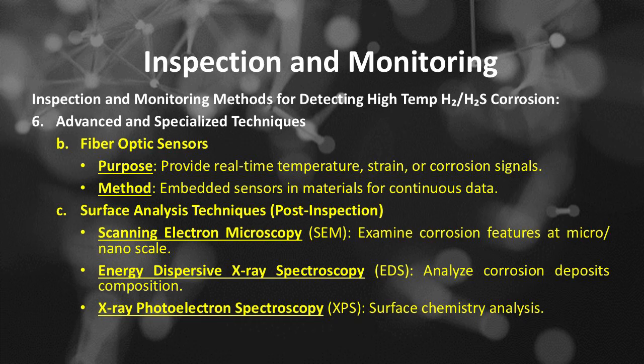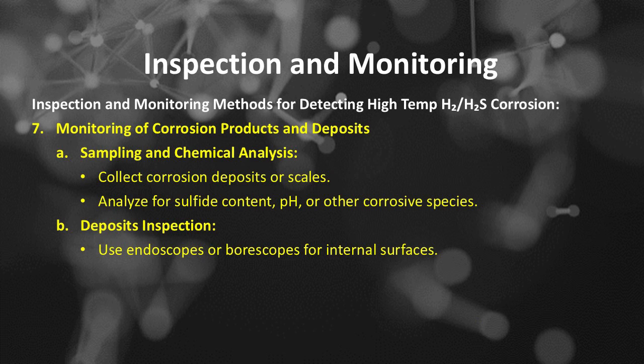The method of using fiber optic sensors is embedded sensors in materials for continuous data. Number C is using surface analysis techniques or post-inspection: scanning electron microscopy, or SEM, to examine corrosion features at micro/nano scale; energy dispersive X-ray spectroscopy, or EDS, to analyze corrosion deposit composition; and X-ray photoelectron spectroscopy, or XPS, for surface chemistry analysis.